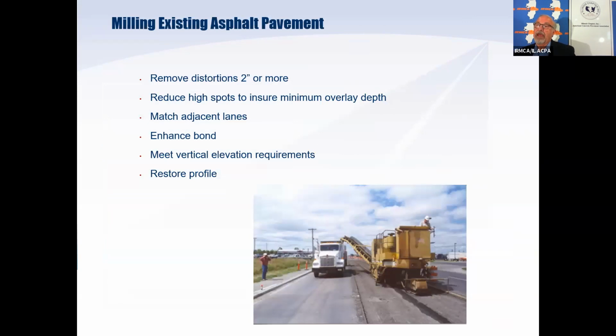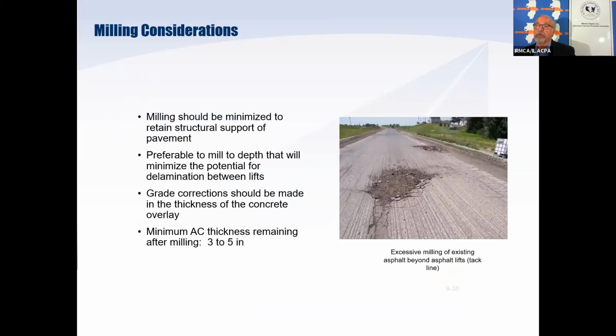So do we absolutely have to mill the asphalt? No, we do not. But it's to your advantage to do that. Milling is relatively inexpensive. You can use the millings, you can recycle those, you can dress the shoulder with them. But it allows us to put down a more or less uniform thickness of concrete, which is important. It allows us to match existing lanes. But the most important thing is it enhances the bond, and the bond being all important.